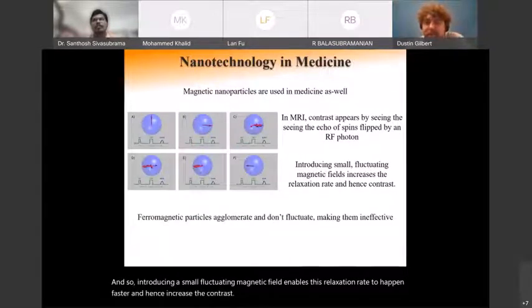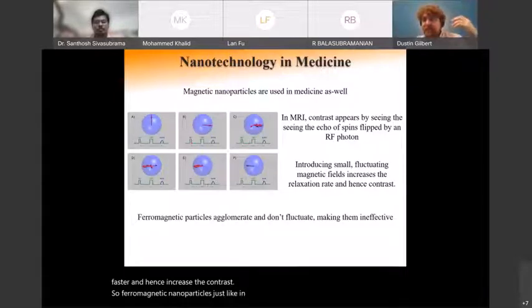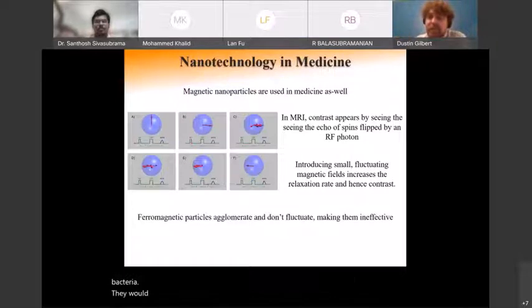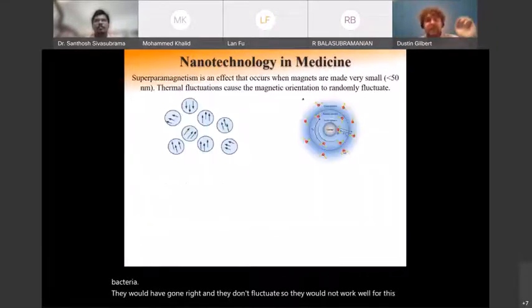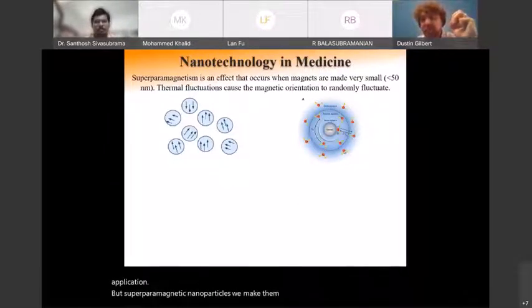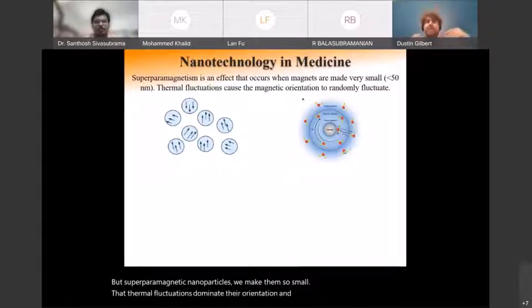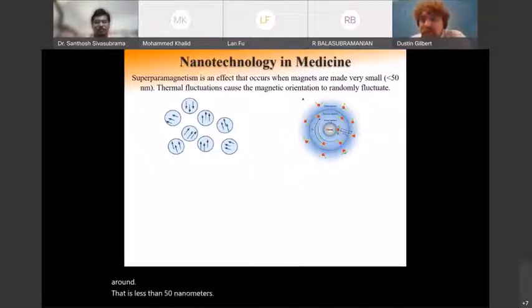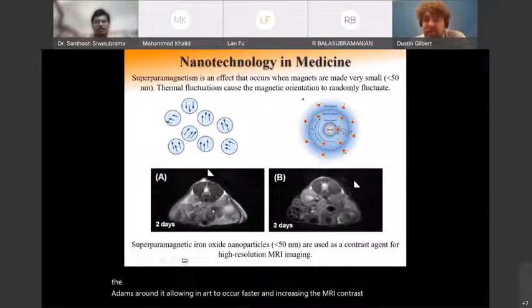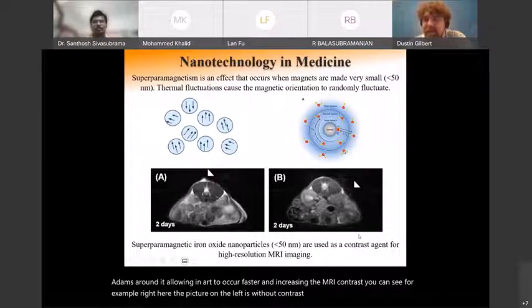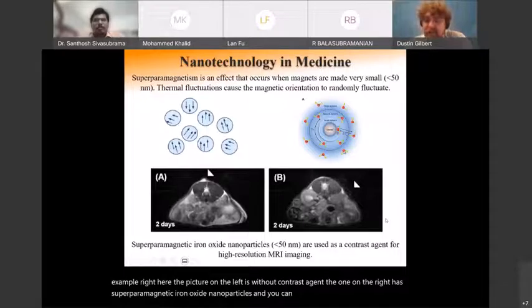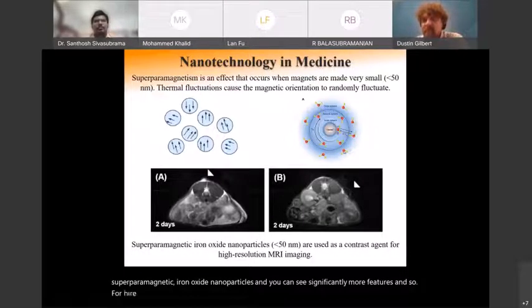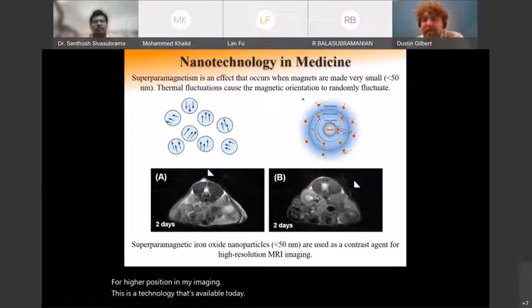So ferromagnetic nanoparticles, just like in the biological systems of birds and bees and bacteria, would agglomerate and they don't fluctuate. So they would not work well for this application. But superparamagnetic nanoparticles, we make them so small that the thermal fluctuations dominate their orientation and they're constantly fluctuating around, that is less than 50 nanometers, do work exactly like that. They don't agglomerate, and they can exchange angular momentum with the atoms around it, allowing the NMR to occur faster and increasing the MRI contrast. You can see, for example, right here, the picture on the left is without contrast agent. The one on the right has superparamagnetic iron oxide nanoparticles, and you can see significantly more features. And so for high resolution MRI imaging, this is a technology that's available today. But superparamagnetic iron oxide nanoparticles also show up in a variety of other medical applications.